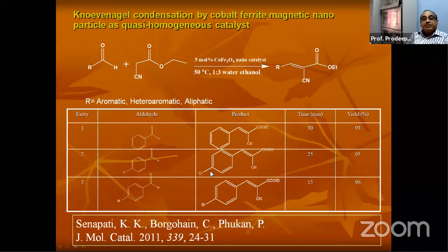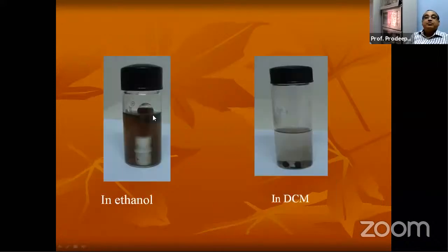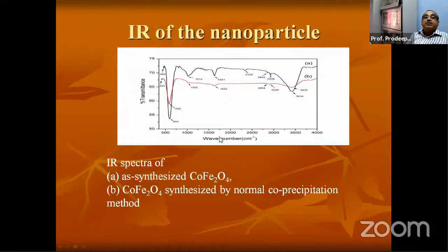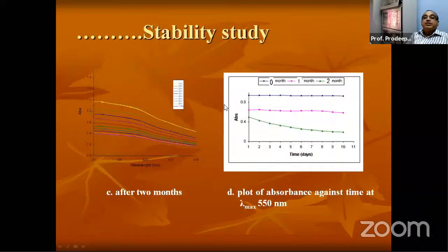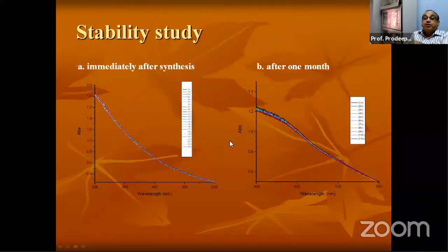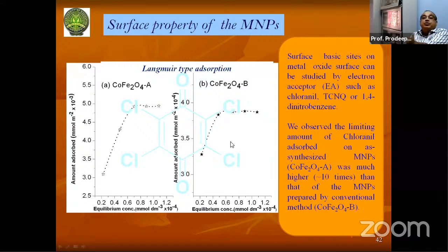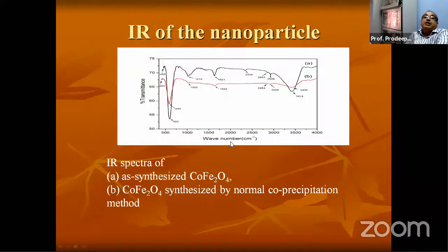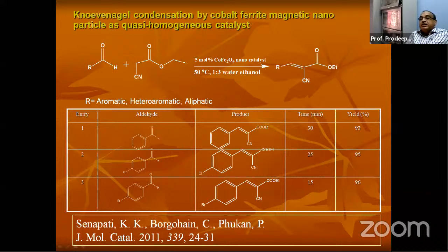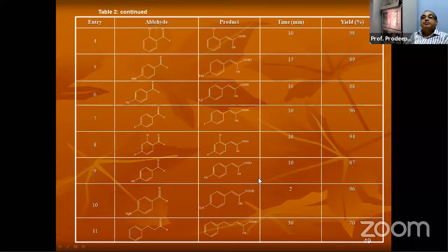Then, when we synthesized this, you can see from here that it shows a surface basic property. So we thought we should do some reaction which can be carried out under base catalyzed conditions. So that is why we started with the Knoevenagel reaction. This is a very simple reaction. You can see at 30, 25, 15 minutes, at 50 degrees centigrade, the yields are very high. And so many reactions we have done.